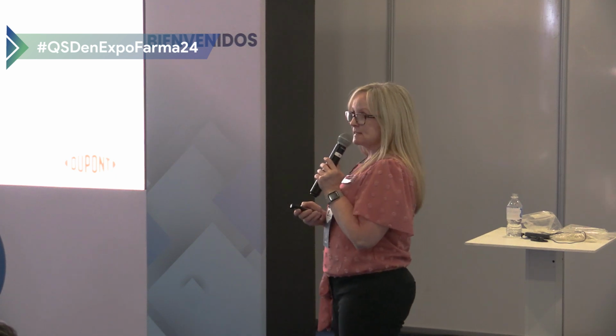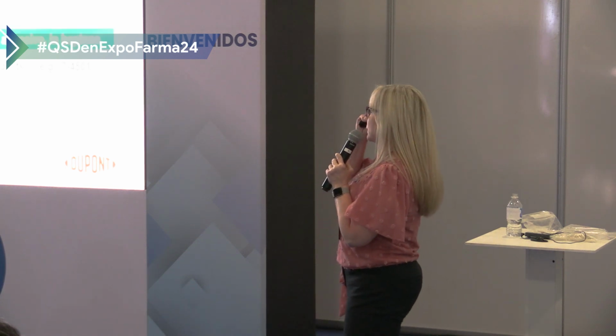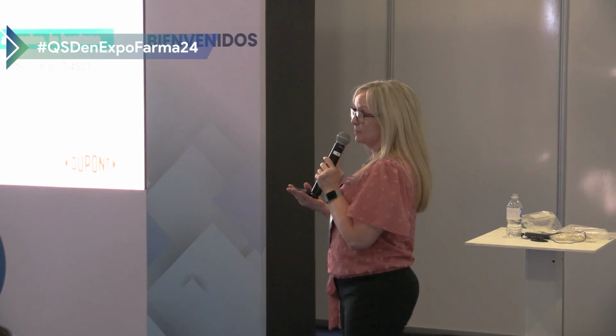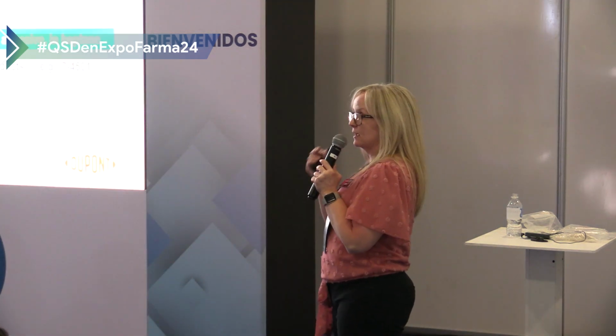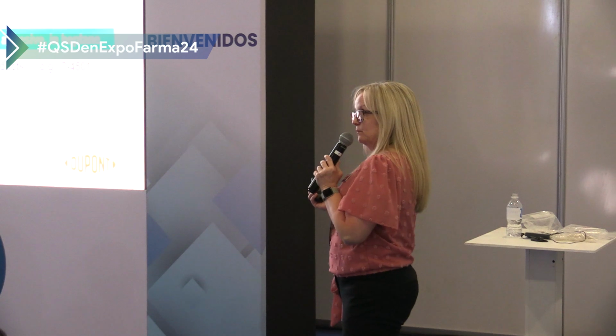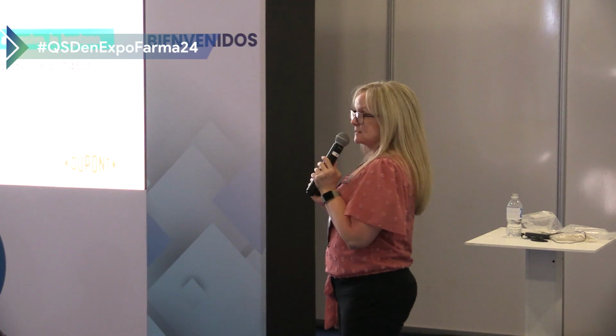So just to give a very basic overview of our bio PSAs, because I know some people have asked about these. With our bio PSAs, we have a tack range, and it's very subjective. So, high, medium, low. But it's very easy to tell the difference. We have some that are amine compatible. We have standard with silanol, reduced silanol content, as well as just our standard PSAs for these. You can see on the left there with the solvents, we have a much larger variety of solvents that we do for these.